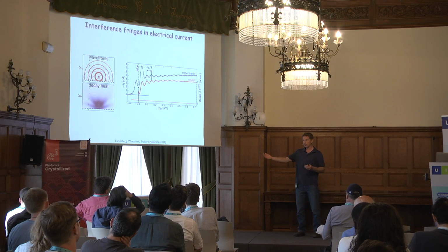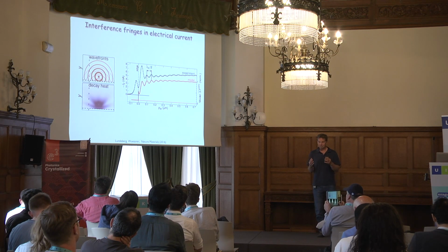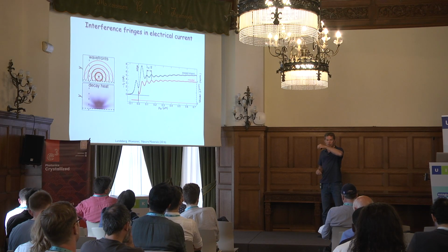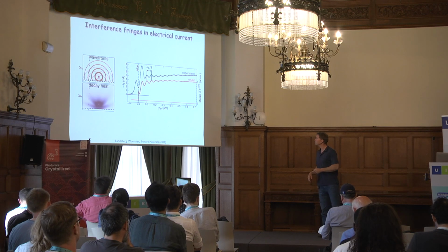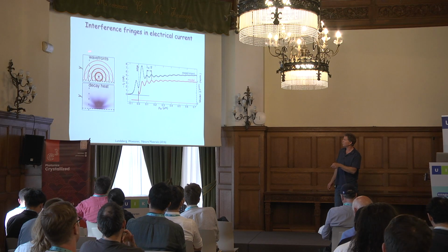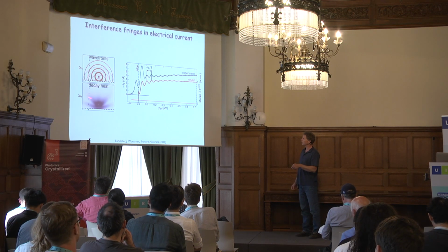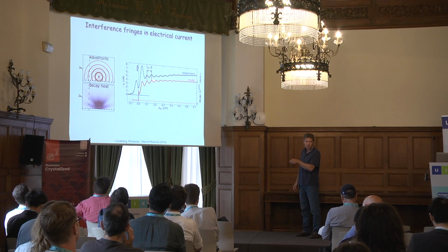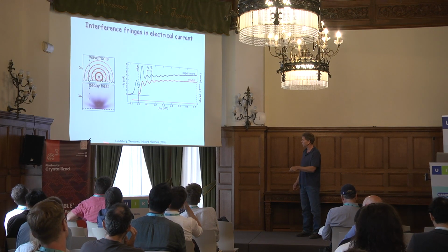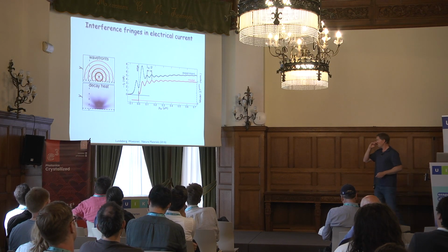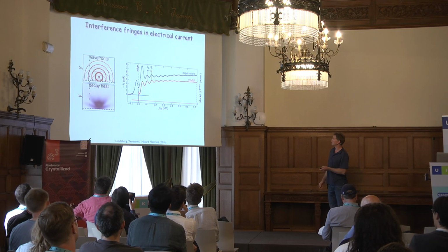Because the plasmon launched by the tip is reflected, as Pablo explained. When they coherently interfere, then there is more heat produced than when they destructively interfere. You can understand this basically from wavefronts of the plasmon, and then from that you can calculate the decay heat, and in that way you can perfectly model the heat generation from this plasmon that oscillates near the edge. All of the details are in this paper, also from Mark Lundeberg, so that you can calculate it very well. It was not predicted, but we were very excited that we can see plasmons in this way.